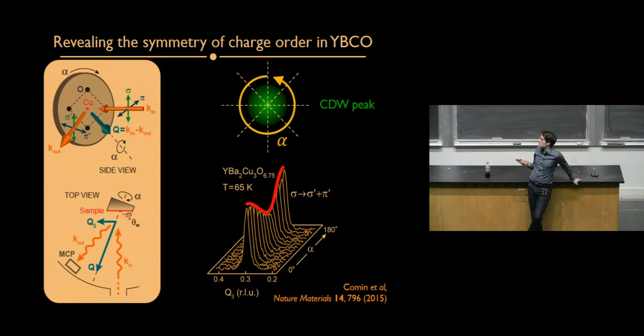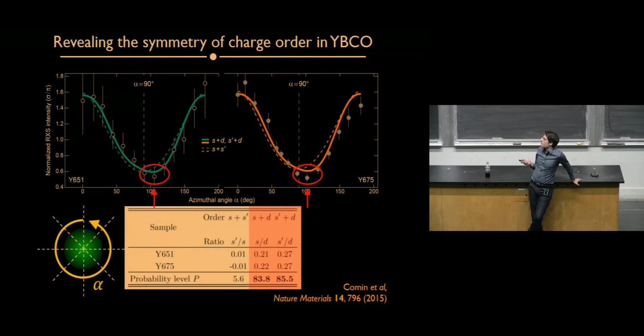And as you can see, there's a clear modulation as we sweep the angle of the polarization with respect to the crystallographic axis. And if we model this change in the intensity as a function of this azimuthal angle of the polarization, which measures different components of that scattering tensor, then we see a fundamental asymmetry here in the sense that the minimum in this change of the intensity is displaced away from 90 degrees, which would be the symmetric situation going from 0 to 180 degrees.